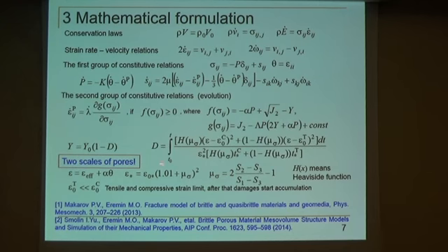Damage is described by this integral and is based on strain behavior and influences the strength of the material, namely cohesion. So when damage approaches unity, then the material is absolutely destroyed.